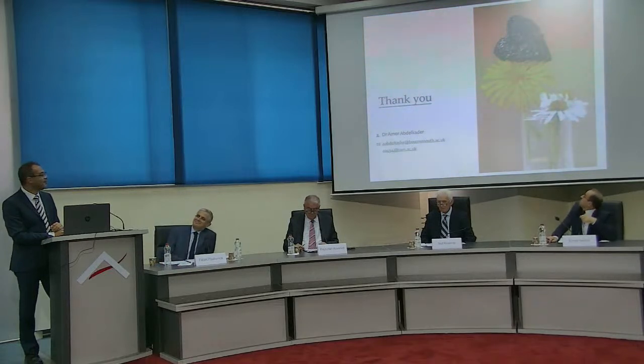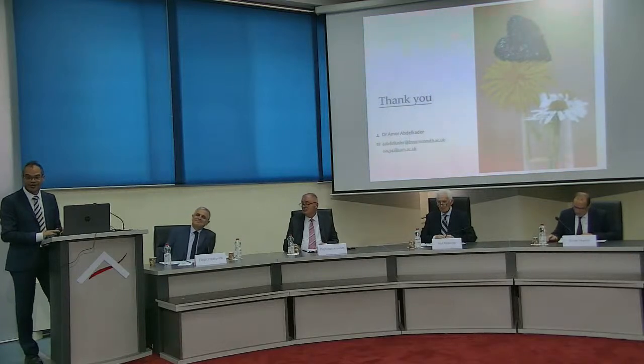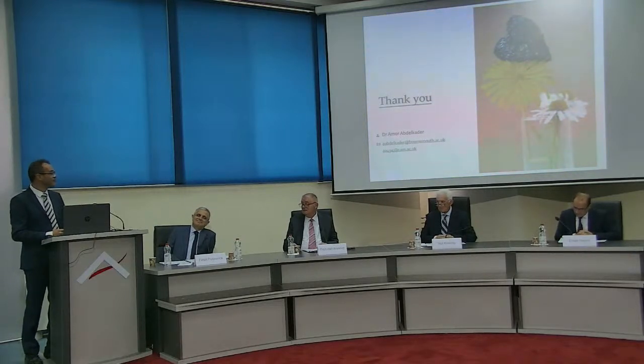Yes, this is actually our foam, which we used for sodium sulfur. It's made of graphene, and as you can see, it's very light. The entire block, one by one, is around 0.6 milligram of the material. That's why they call it aerogel. You can see it stand nicely on the petals of flowers without damaging them. I made it, of course, in a love heart, simply because it matches my name, but also just to show basically we can form it in any different shape that we would like. So it's for fun, nothing really serious, but it's the same exact structure we used for sodium sulfur battery.